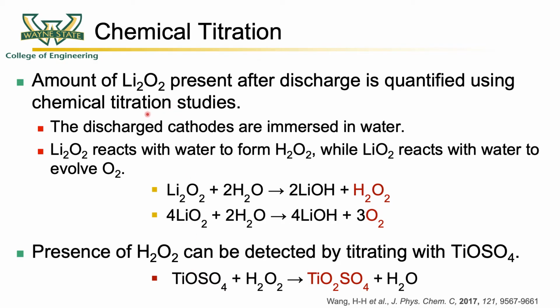In order to understand the discharge product distribution, we turn our attention to quantitative techniques involving chemical titration. Chemical titration takes advantage of the reaction of Li2O2 with water, leading to the formation of lithium hydroxide and hydrogen peroxide. On the other hand, lithium superoxide, or LiO2, reacts with water, leading to the formation of LiOH and evolution of oxygen as opposed to the formation of H2O2.